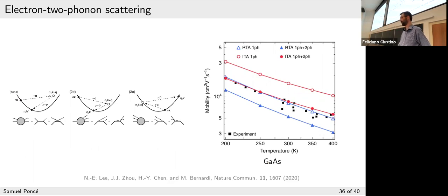So I cannot say, but based on the fact that it works well for other materials, it's true that gallium arsenide is very difficult to describe, because DFT doesn't do a good job at describing the effective mass. It's so small that it's very tough. The hole is fine, but the electron effective mass of gallium arsenide is very sensitive.